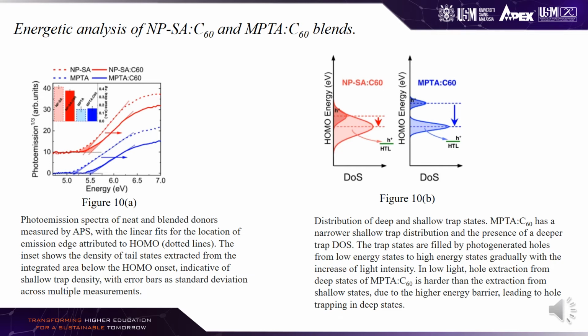Figure 10b shows the distribution of deep and shallow trap states. MPTA carbon-60 has a narrower shallow trap distribution and the presence of deeper trap states. The trap states are filled by photogenerated holes from low energy states to high energy states gradually with the increase of light intensity. In low light, hole extraction from deep states of MPTA carbon-60 is harder than extraction from shallow states due to the higher energy barrier, leading to hole trapping in deep states.